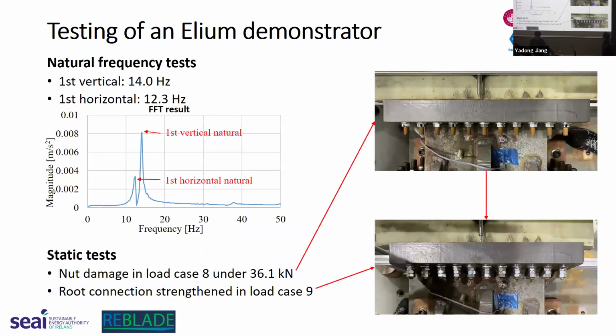Here is a slide summarizing the testing of the second Elium demonstrator. This demonstrator should be fully recyclable. As Conor said, from the mechanical tests there is no significant difference between the glass epoxy and glass Elium, and this is also reflected in the test results. The natural frequency is 14 Hertz, compared to 13 Hertz for the previous epoxy demonstrator. So it's quite close. Similarly, we have similar stiffness for the 2 demonstrators, which I will mention later.